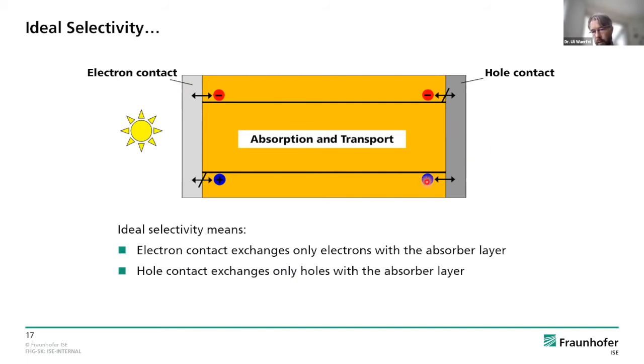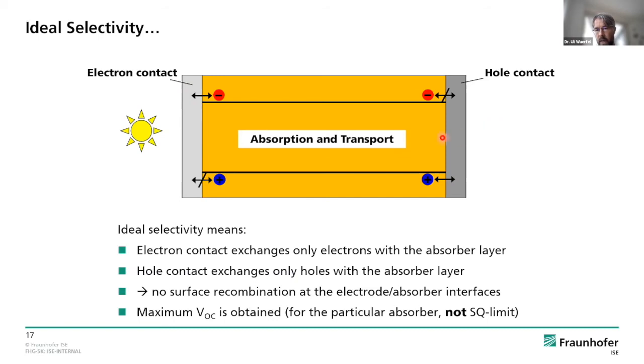And for the hole contact, we need it to be vice versa. We need a good exchange with the valence band, so holes are exchanged here, and no electrons in the conduction band. Then if we realize this, we have no surface recombination at the electrode-absorber interface, and we achieve the maximum open circuit voltage for this particular absorber. It's not necessarily the overall limit, which is called the Shockley-Queisser limit. This is when electrons and holes can only recombine radiatively. But you have maybe some impurities here, and it's the best you can achieve with your absorber. It means that putting the electrodes on the absorber does at least not lead to additional surface recombination.